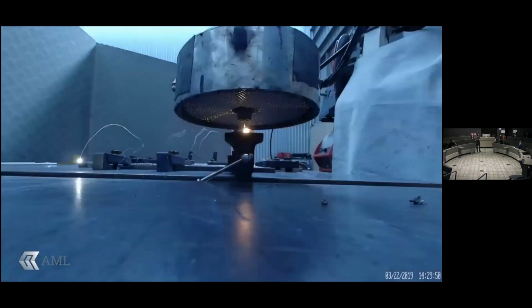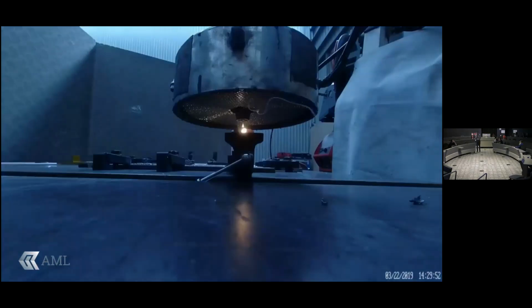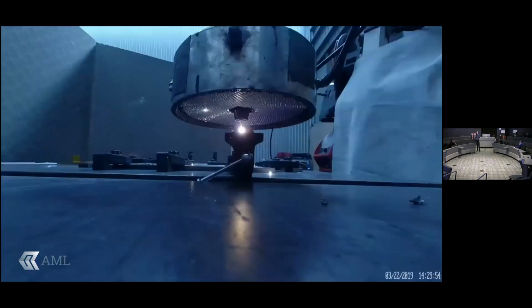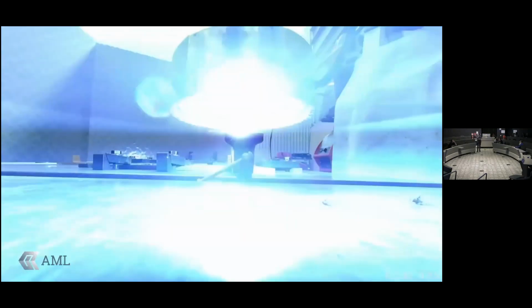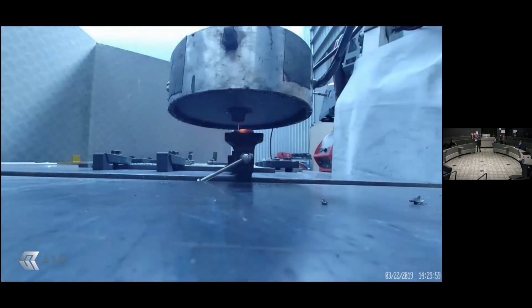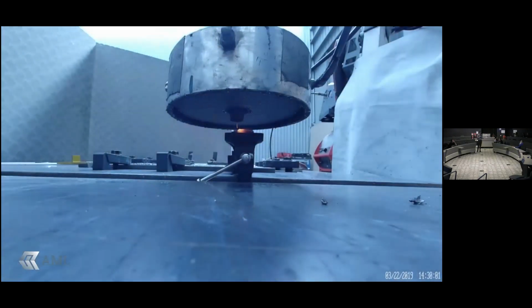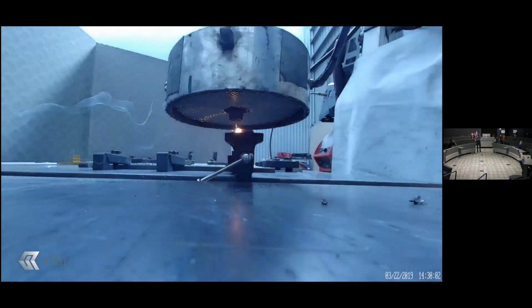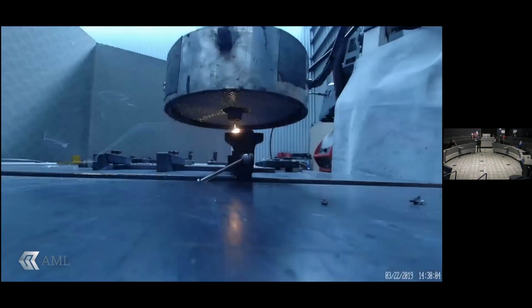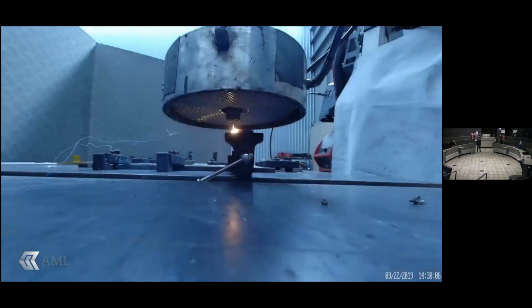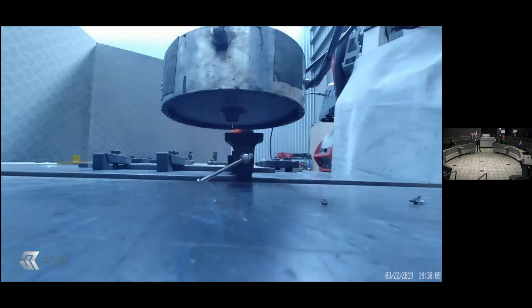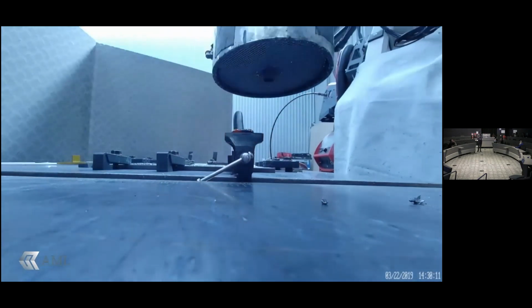Also to note is that titanium oxidizes very quickly, and as a consequence of that, you need to shield the environment, otherwise it oxidizes very quickly. We do that with a shielding system we developed in the UK, and this is our current incarnation of it.